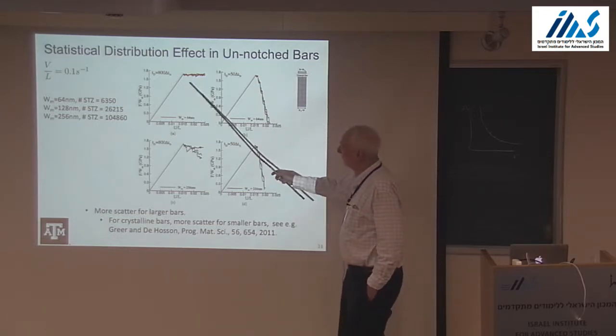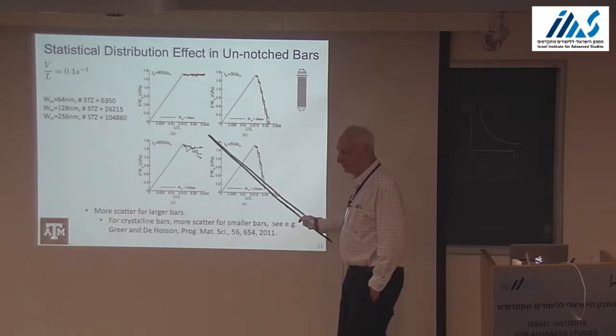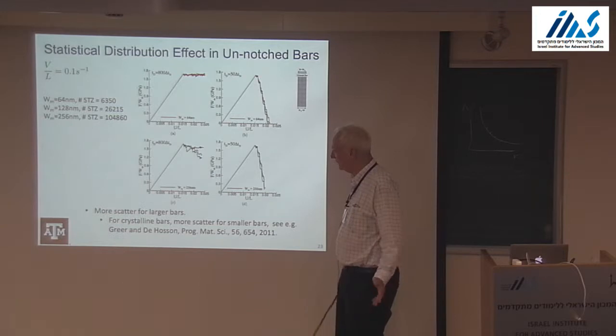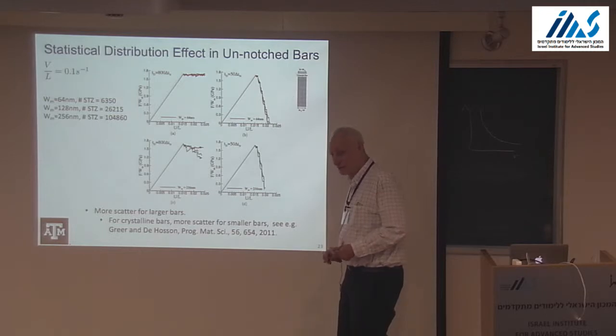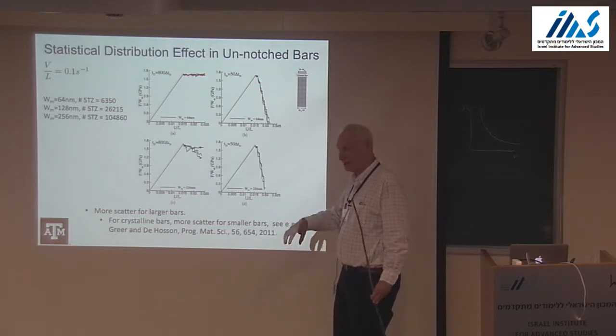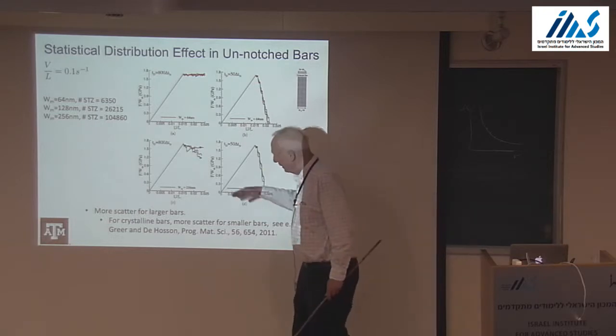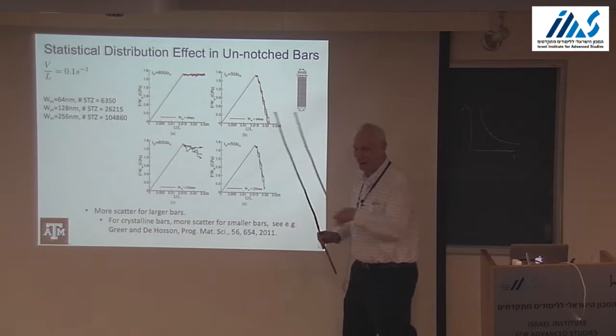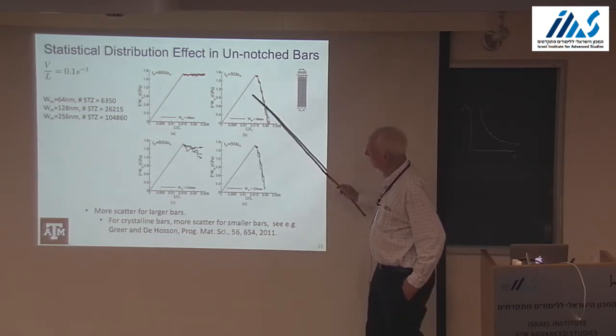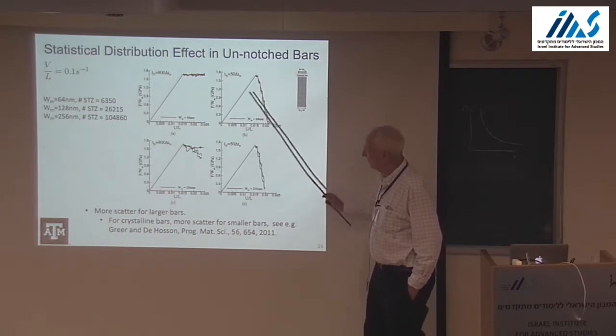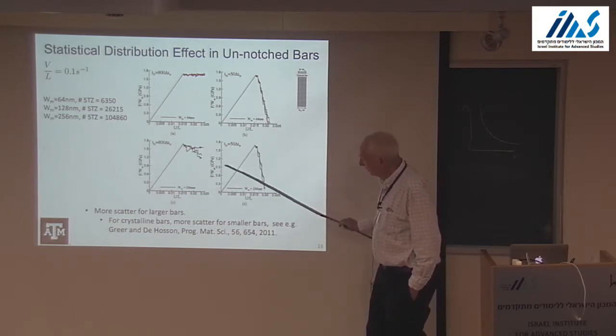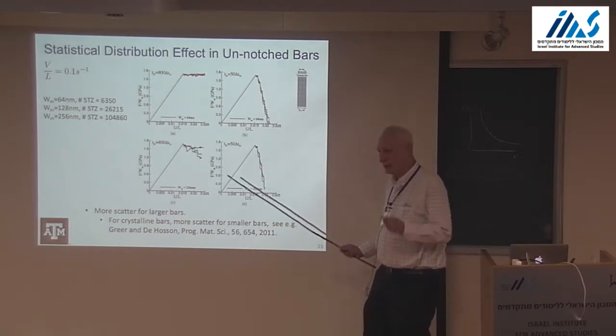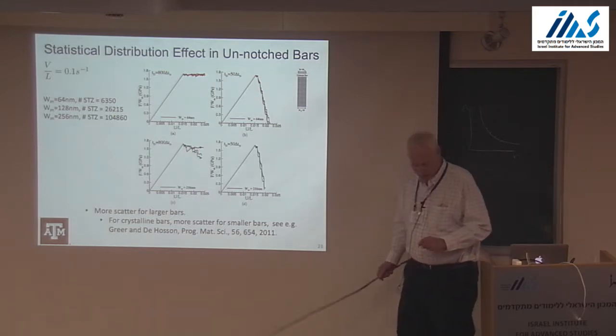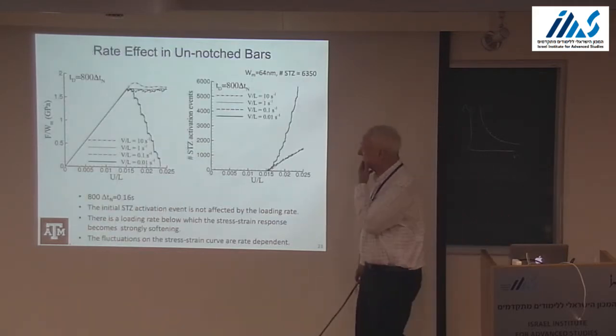So what are the statistical effects? What we find, which was surprising to us, and maybe not so surprising, is we get more scatter for larger bars than for smaller bars. Just the opposite of what happens with dislocations, where you see more scatter for smaller bars. Here we see more scatter for larger bars because once these avalanches start... Smaller bars, practically no statistical effect, at least in what we've looked at. Larger bars, depending on this reactivation time, give more different results. So there's a statistical effect, the opposite of dislocations.